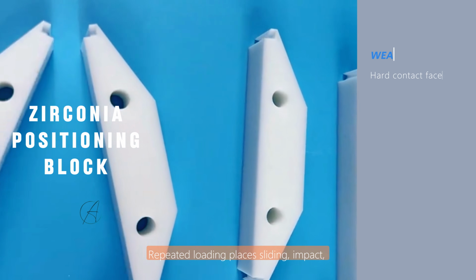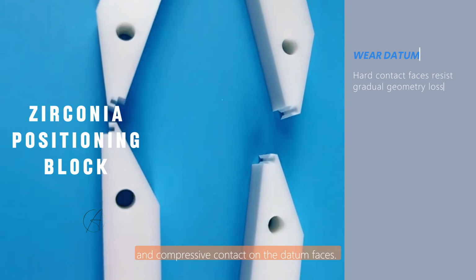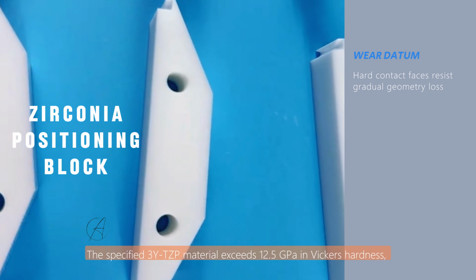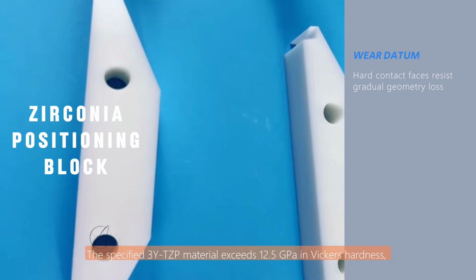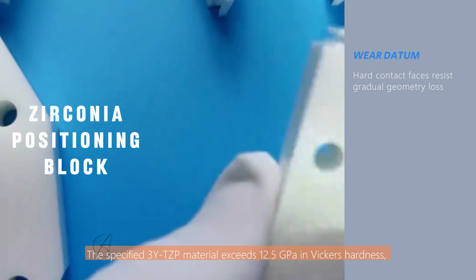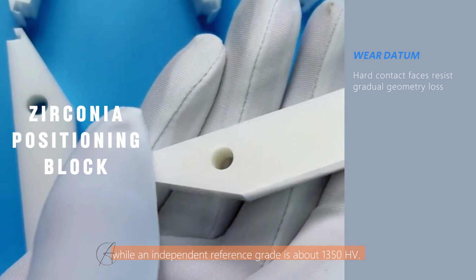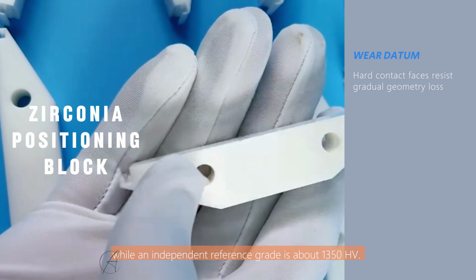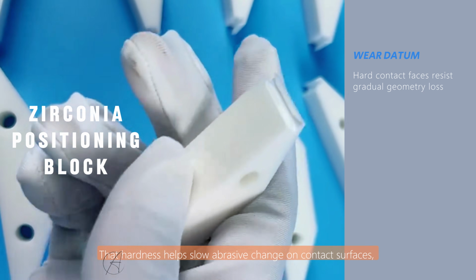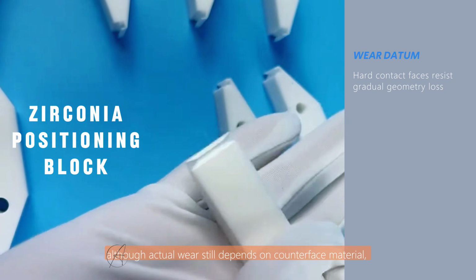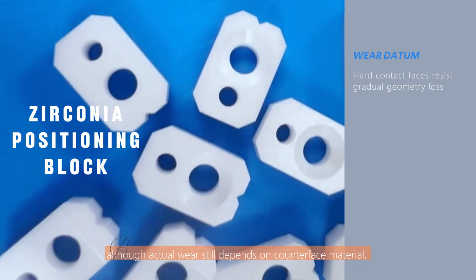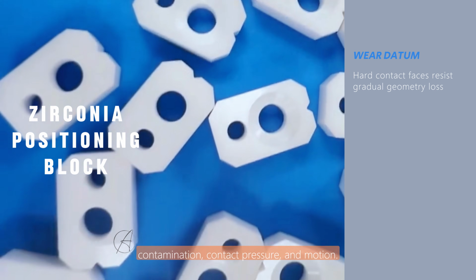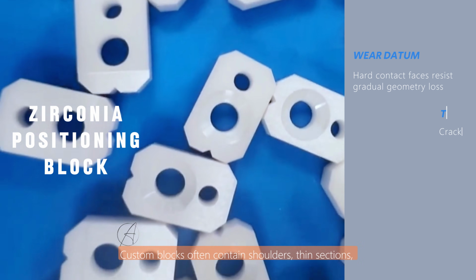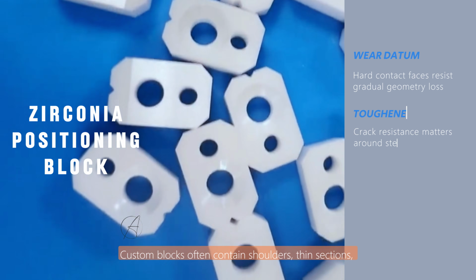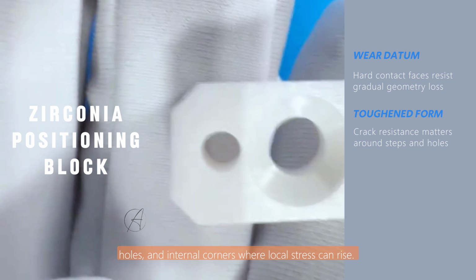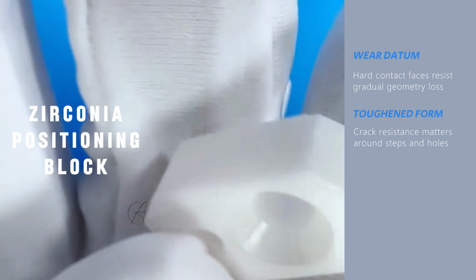Repeated loading places sliding, impact, and compressive contact on the datum faces. The specified 3Y-TZP material exceeds 12.5 gigapascals in Vickers hardness, while an independent reference grade is about 1350. That hardness helps slow abrasive change on contact surfaces, although actual wear still depends on counterface material, contamination, contact pressure, and motion. Custom blocks often contain shoulders, thin sections, holes, and internal corners where local stress can rise.